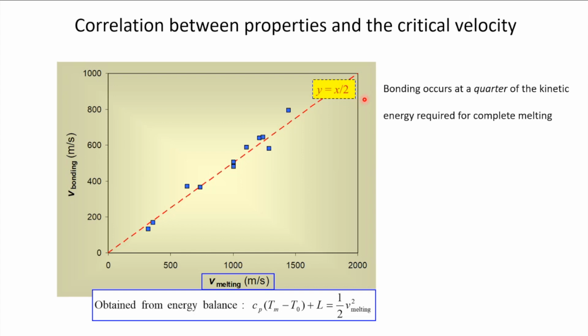Still, it doesn't tell you anything about the mechanism, because it could or could not involve melting, because it's a highly localized deformation process. But what it does tell you is that thermophysical properties are relevant. So if you have particles at higher temperatures, they would probably bond better because of this correlation.